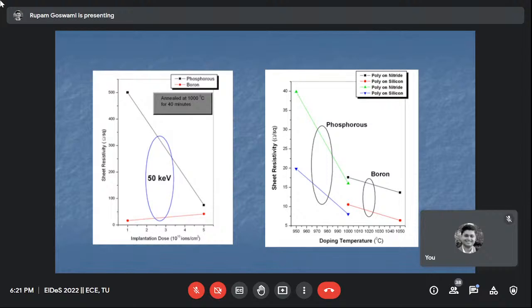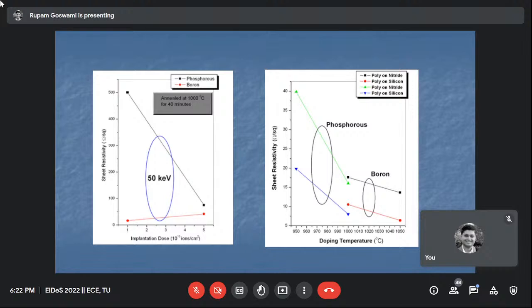So when it is on silicon, it gives the lower sheet resistivity, and when it is on an insulating substrate, then actually it is separated from silicon, isolated. So the sheet resistivity is a bit higher in both the cases, either it is phosphorus doped or boron doped. Generally we use boron because of the piezoresistive coefficients. But in this study we knowingly did this to know what happens to the electrical performance of the layer when we use different doping species. Next, please.